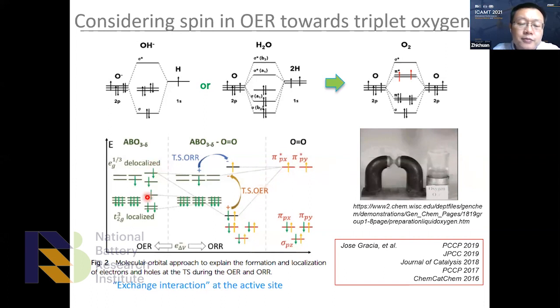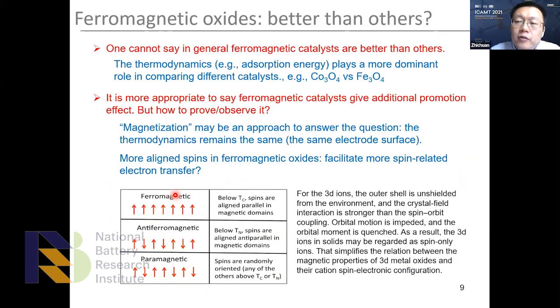And further, Jose pointed out there is a spin-selected electron transfer within the catalyst. For example, he used perovskite oxides as models. If we follow that kind of logic, we would draw the conclusion that ferromagnetic oxides will be better than others. For example, we can classify catalysts based on magnetic property: ferromagnetic catalysts are better than antiferromagnetic or paramagnetic ones. So I would say, as an electrochemist, I would disagree with it.